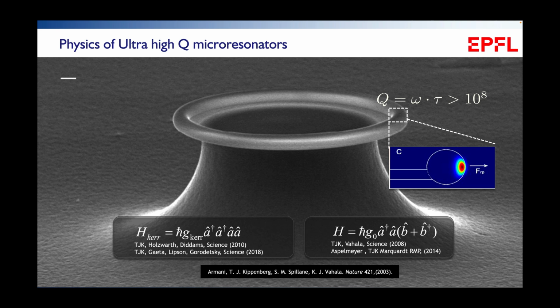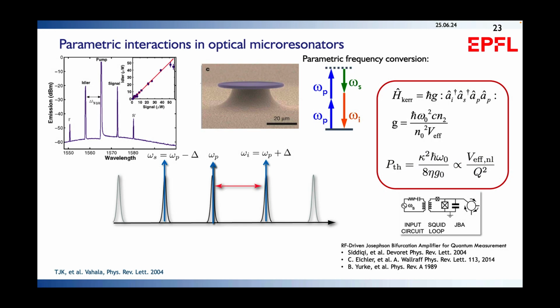And so these devices, despite being very simplistic, have a couple of very interesting aspects. One is they have a mechanical mode that couples to radiation pressure, which we'll not discuss. But the other part is that glass itself has a Kerr nonlinearity. And this Kerr nonlinearity, once you pump the material strongly enough, can give rise to photon pair generation. And so this was discovered, as I said, now 20 years ago in optical microresonators. So when you pump a microresonator, a CW laser starts to generate signal-idler sidebands due to this parametric frequency conversion process.